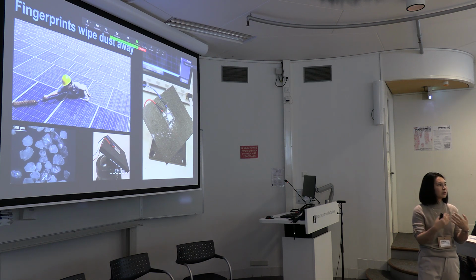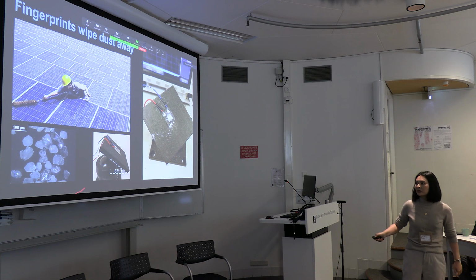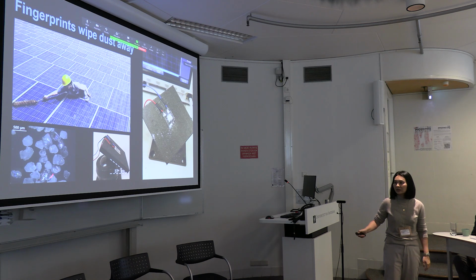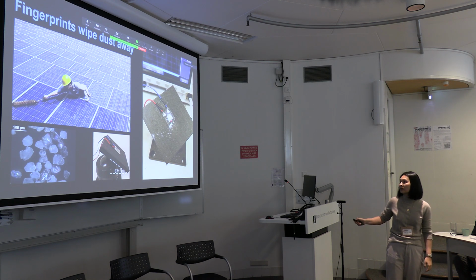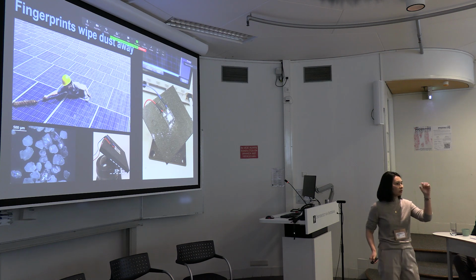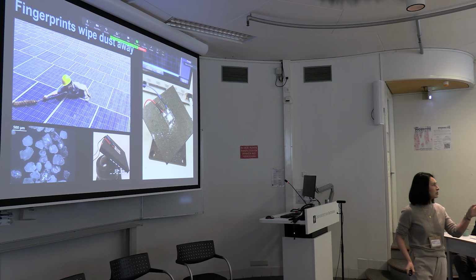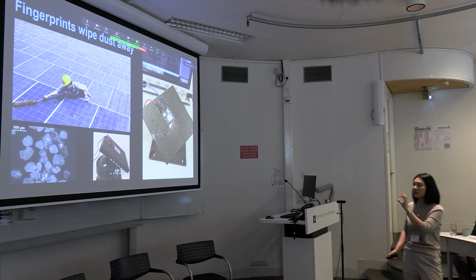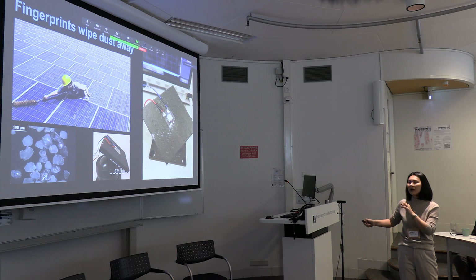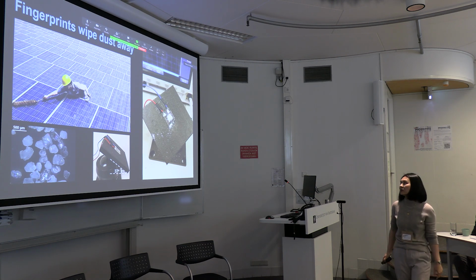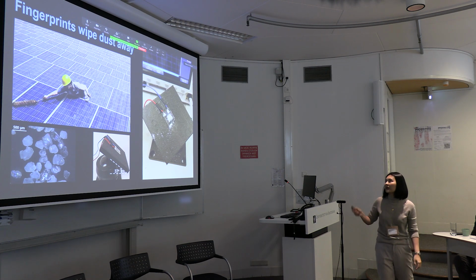Can that be used for self-cleaning? For that reason, we bring sand that is around 100 micrometers in diameter and put it on our surface. In the lab, we quite often make samples of 3 by 3 centimeters. In this extreme case, the area covered by the white sand is only 1 centimeter by 1 centimeter. Then we start to apply an electrical field.